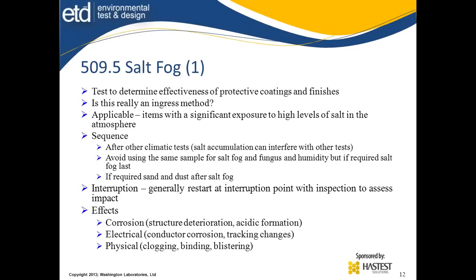The sequence is after other climatic events, meaning salt can interfere with other tests, so you do this pretty late into the sequence. Avoid using the same test sample for salt fog and fungus and humidity, but if required, do the salt fog last. You have to pay attention to the cleaning for these other things. Fungus and humidity, make sure that you've got this thing inspected well before you go do the salt fog, because the ill effects of humidity have to be given time to manifest themselves before you go in and apply the salt and cause the problems.